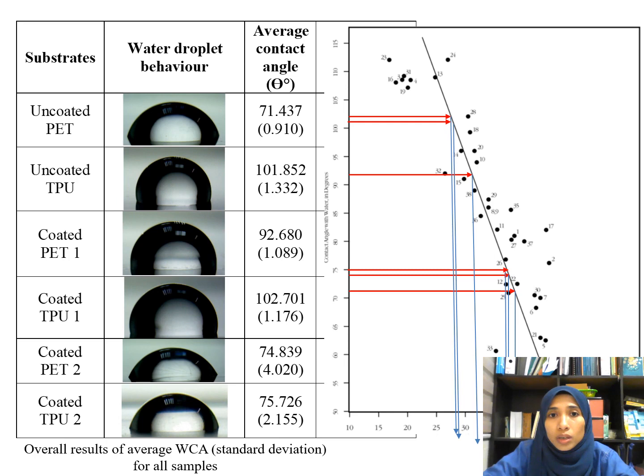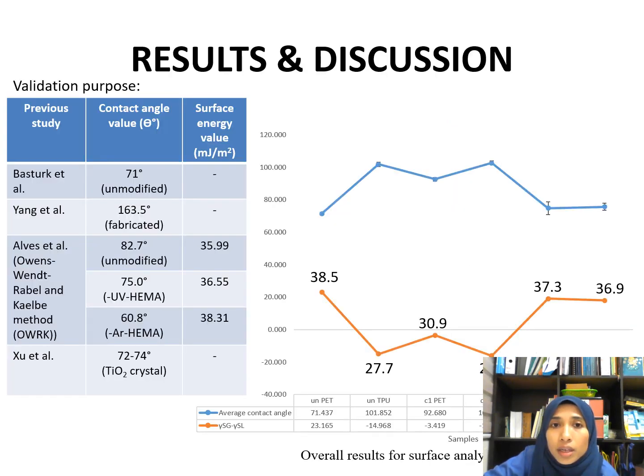So you may see that the water contact angle for uncoated polymer is lower than the coated one. Actually, the coated one for type 1. For type 2, uncoated polymer, the value of contact angle is larger than the coated one. So from here, as I said earlier, the value of average contact angle is adjoined to the regression line, then we drop it down to the x-axis, so we can get the value of surface energy analysis. This is the result and discussion for this research.